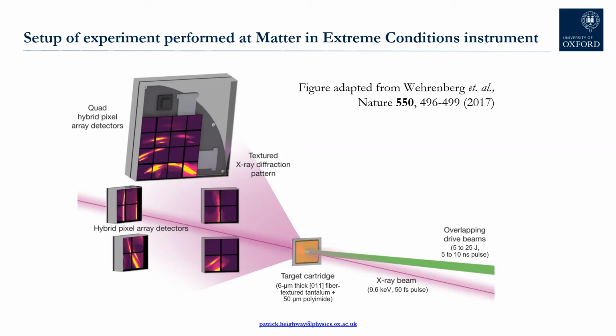So the experiment in question was conducted at the matter in extreme conditions end station of LCLS, and the configuration is a pretty standard one. Our targets comprise 6 micron thick polycrystalline tantalum foils with a 50 micron polyimide ablator on their front surface that are shock compressed to about 1 megabar with a set of high power pulsed optical lasers.